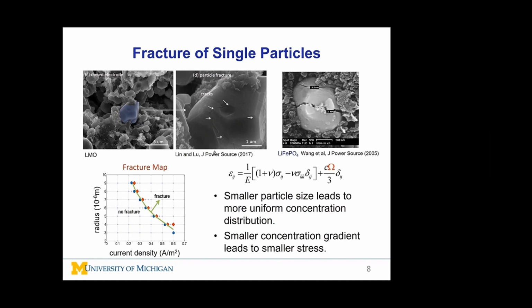The behavior of fracture inside a single particle is known. The strain includes a mechanical strain part and a strain associated with the volume of lithium ions. Here, C is lithium ion concentration in the particle, and omega is the partial molar volume of lithium ions. This latter part is similar to thermal strain.